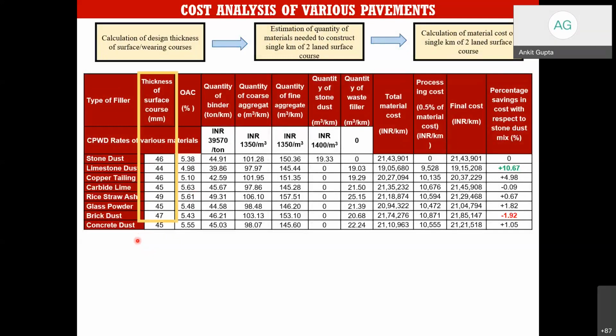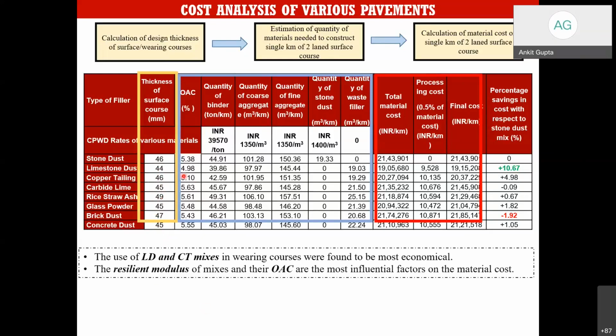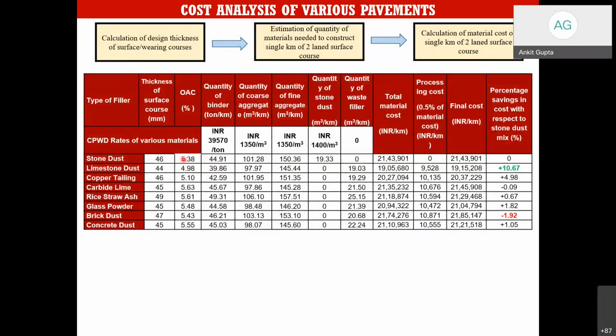Only the surface course properties which have been evaluated in the laboratories, we have used for the analysis, and we could find out that there are some changes in the thicknesses. Like the minimum thickness was around 44 mm and the maximum thickness is 49 mm. Okay. Now these are the few different values of the optimum asphalt content or the optimum bitumen content, which we have measured from our Marshall mix design. These are the quantity of the binder. These are the CPWD rates which we have taken from the CPWD manual. And this is how we could find out the quantity of the binder, quantity of the coarse aggregate, quantity of the fine aggregate, quantity of the stone dust.